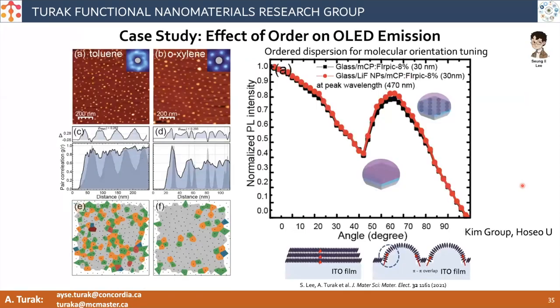Another example is the effect of order on the orientation of molecules for an organic light emitting diode. The difference here is very subtle. There's not a huge difference in this phase. We haven't optimized that away. But the principle is basically by introducing these nanoparticles, you can start to see a modification of the tilt angle of the molecules, which changes the emission profile slightly. And by tuning again from purely ordered to disordered, you can see the impact of whether having a periodic roughness or a Gaussian roughness makes a difference in terms of this organization, which is important for emission properties.